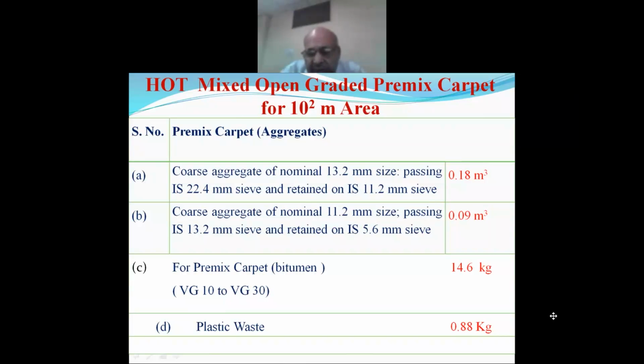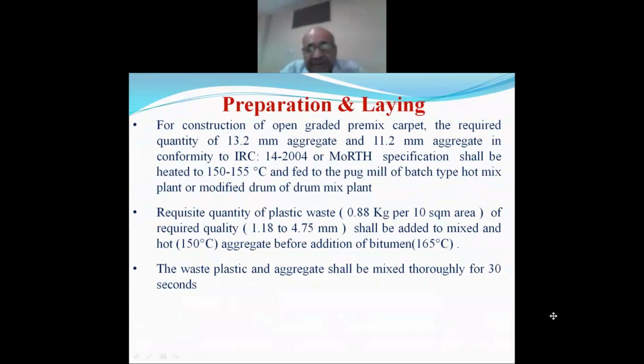Modified hot mix plant shall be used. A device for addition of the plastic shall be attached with the hot mix plant, preventing exposure of the plastic to the flame. Plastic shall be free from PVC and size shall be maintained. Black colored plastic shall be eliminated. Plastic waste shall be added over the heated aggregate before addition of the bitumen. Temperature shall be 10 degrees higher than the normal construction temperature and no reduction in the bitumen content. Some people claim reduction of the bitumen content, but there is no reduction in the bitumen content.